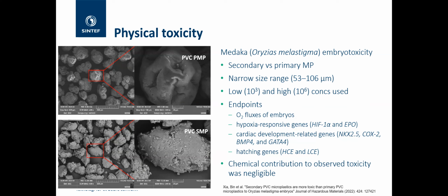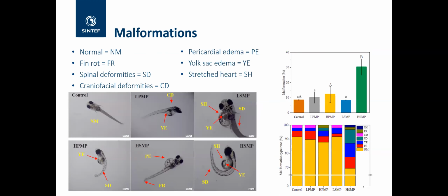We isolated the same size range for both particles, so it's 53 to 106 micron, and then we used a couple of exposure concentrations, a high and low. We exposed these to Medaka fish embryos, and we studied some endpoints that we thought might be of interest. So this is O2 flux, some hypoxia responses, cardiac development genes, and hatching genes. I won't go into detail, but I just want to say that the chemical contribution, we were aware of this, particularly with PVC. So it was validated and tested that the way we set the experiment up, there was no chemical toxicity here. It was a direct comparison on the physical toxicity.